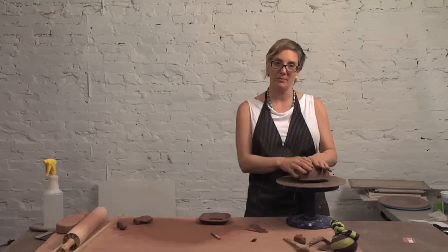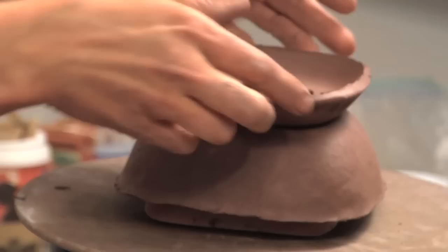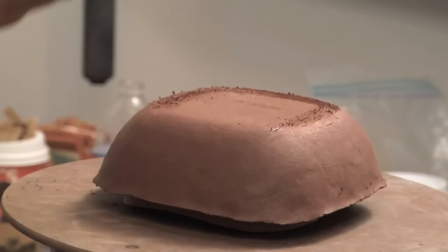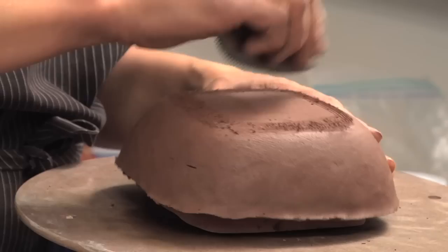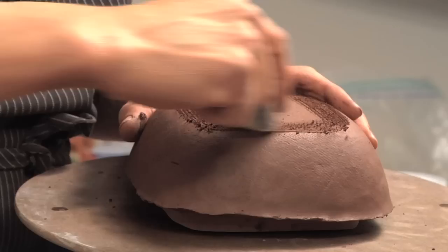My pieces are off the mold. Here's the base — these are all a little less than leather hard, something like that. I've got the body of the pot resting on top of the bisque mold because I'm going to be putting some pressure on it. Now I'm going to attach the pedestal part. First thing I need to do is score the bottom and slip and score this really well, because basically I have two drier pieces of clay going together and I need them to stick. So no wussy scratching — very aggressive scratch marks here because you really need the clay to bond together.